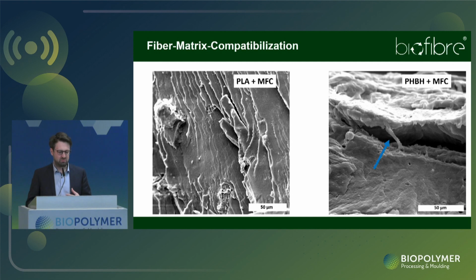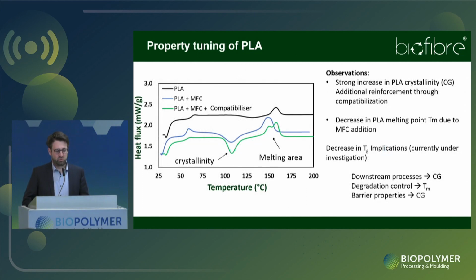That's why we pretty much tuned around between being really hardly bound to the matrix, and to have compatibilization that is really making the fibers adhere to the matrix material, since the polarities are in many cases quite different. What we saw as well is that once we introduce those nanoscale fibers, they have dimensions in the nanoscale, in the microscale. They are as well working as seeds for crystallization. You can drastically enhance the crystallinity, as well the cycle time in the injection molding process.